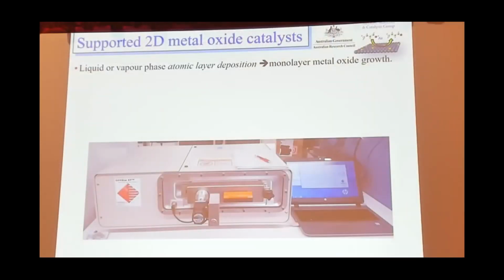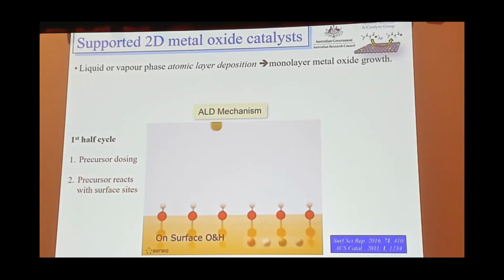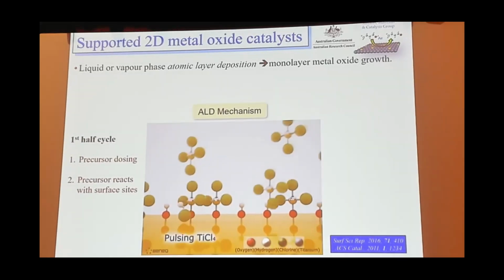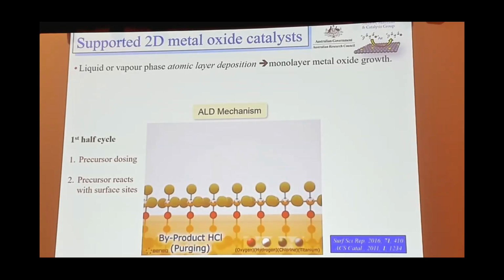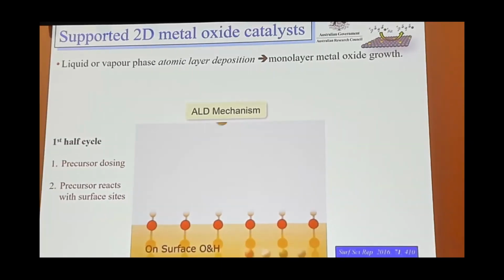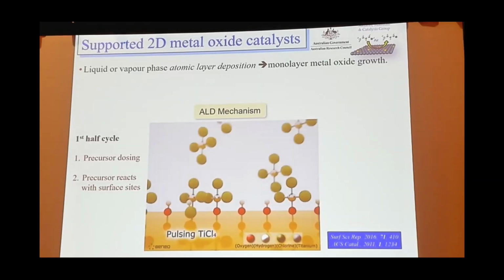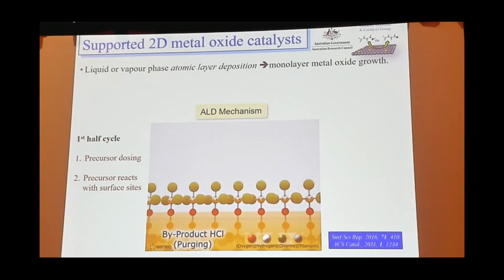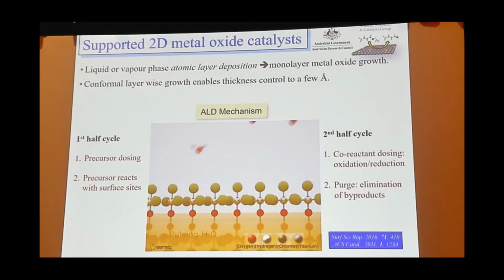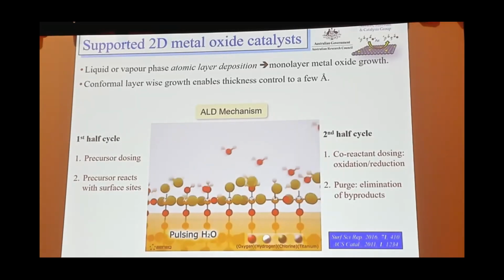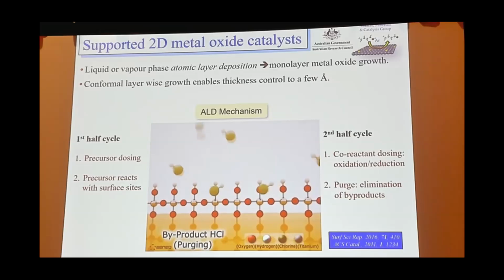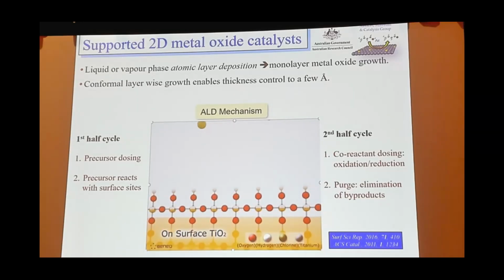We've been using a lot of surface deposition approaches, starting off with work depositing thin metal oxides from the liquid phase, and more recently we've been exploring the use of atomic layer deposition from the vapor phase to grow metal oxides. For those of you not familiar with atomic layer deposition, essentially you start off with your support, which is highly hydroxylated, and then you put in your precursor, maybe a metal chloride. It's a self-limiting process where the metal chloride comes in, reacts with the hydroxyls, and grafts on the surface. As long as it's dry, you won't get a second layer going down while that is a halogenated surface. You then put in another pulse of water that removes the residual chlorine to give you a metal oxide, and then you can repeat that for subsequent coatings.